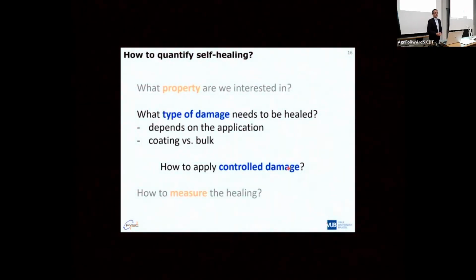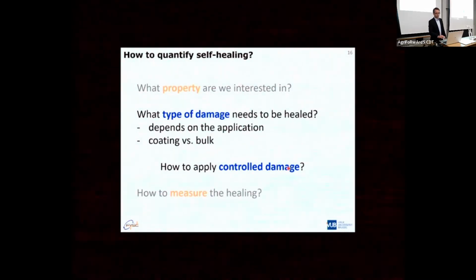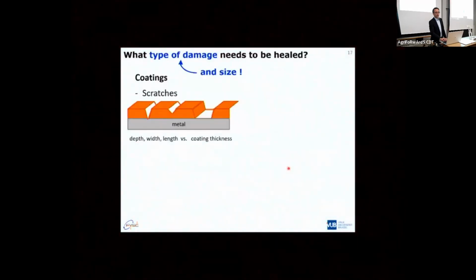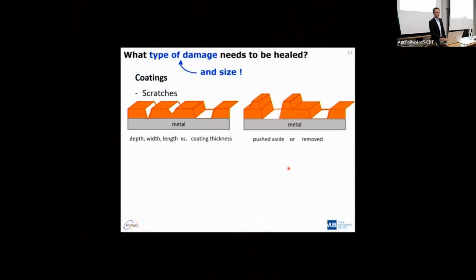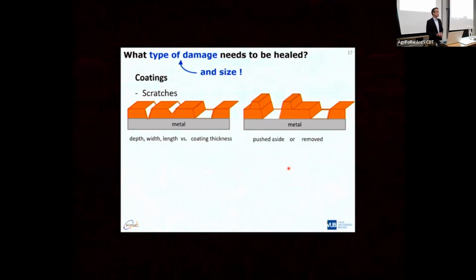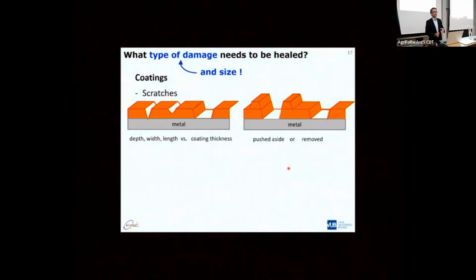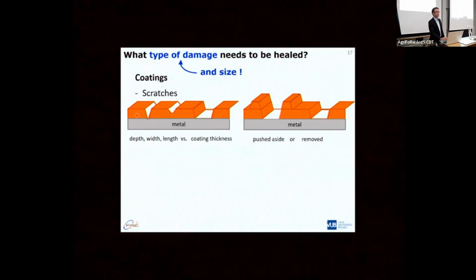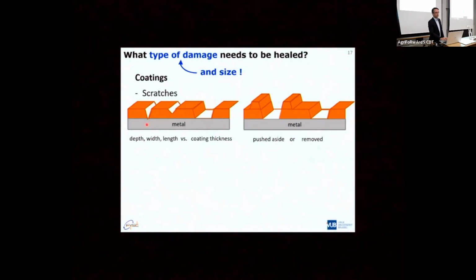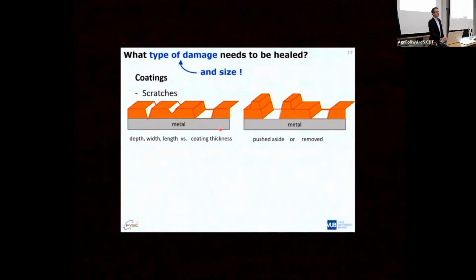And then you need to look at what kind of damage needs to be healed. That will depend on the application, and I will just highlight this with examples from coatings and from bulk. When you look at a coating, scratches are one of the most common kinds of failures, of course. When you start applying them, you need to do this in a controlled way. So you will need to control the size of the scratches that you are applying, the width of the scratches, the depth of the scratches. Are they going to the metal or not? Are they going through the oxide layer or another layer that you put on the surface of the metal or not? All this will influence the way the system will behave during the healing and will influence the results that you get.